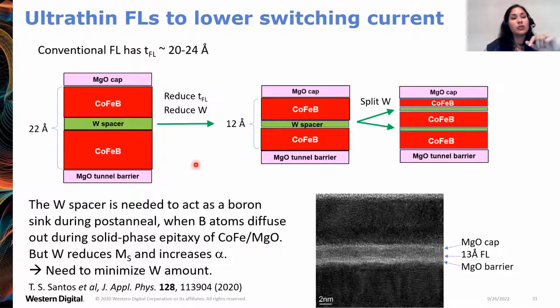The boron atoms want to diffuse to this heavy metal spacer. Otherwise, having this heavy metal here is going to degrade the magnetic properties of your cobalt iron boron. It's going to reduce the saturation magnetization and increase the damping parameter. So we want to minimize how much tungsten is needed there. Our strategy for doing this is just to altogether reduce the thickness of the free layer. And we were able to reduce it substantially down to 12 angstroms here, so that the tungsten layer is very, very thin. And we found that the magnetic properties improved even further if we take this single tungsten spacer, keep the same thickness, but then split it into two thinner layers.